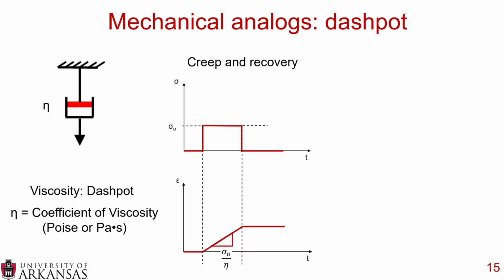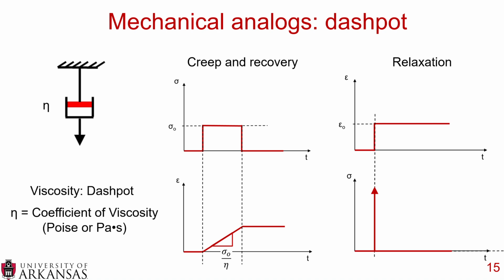You can see that the increase in strain is simply that applied stress divided by eta, but then when you remove the stress, the strain stays on, so it does not decrease again. And with relaxation, you apply some sort of constant strain at some time, and it's a very interesting response. Essentially what happens is the stress goes to infinity immediately, but then immediately drops down to zero. So you've essentially maxed out that dashpot by putting the maximum stress on, and then it doesn't matter how much more strain you put on there, your stress will be zero.